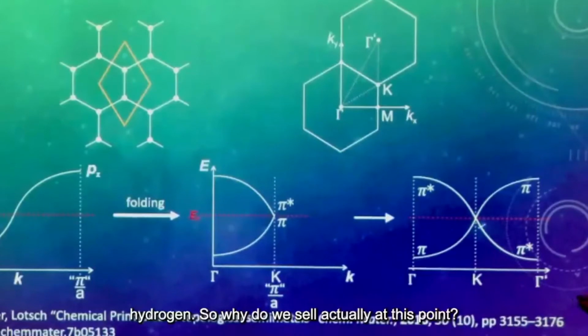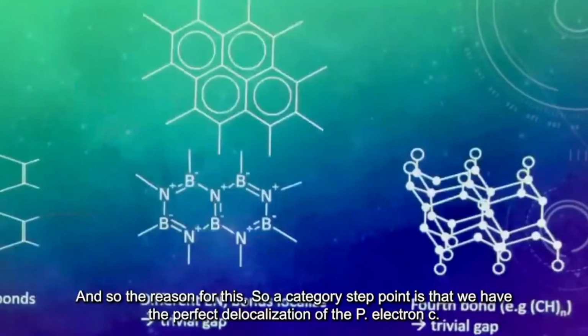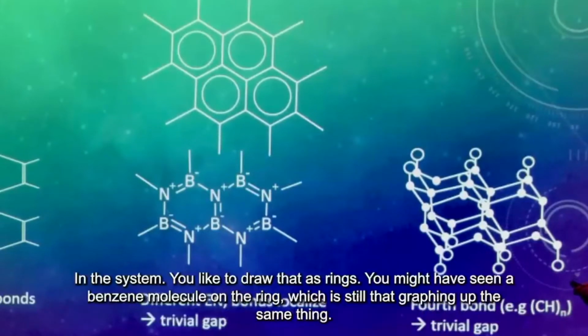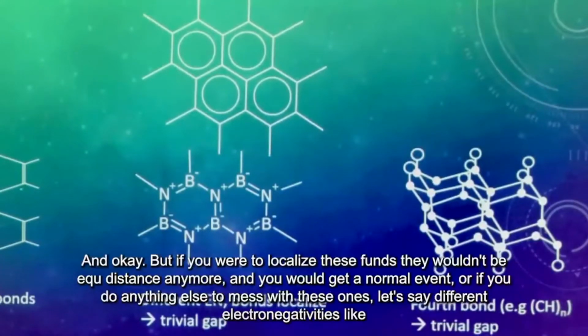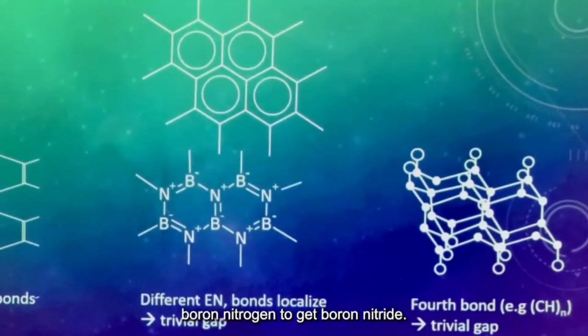So why do we stop actually at this point? The reason for this from a chemical standpoint is that we have the perfect delocalization of the p electrons here in the system. We like to draw them as rings. You might have seen a benzene molecule once, the ring. Graphene does the same thing as benzene. But if you were to localize these bonds, there wouldn't be equidistance anymore, and we would get a normal band gap.